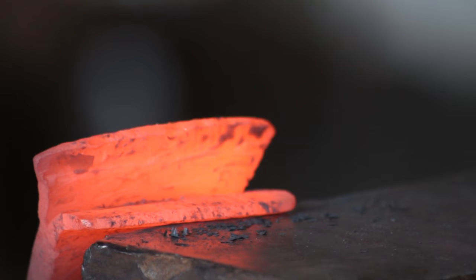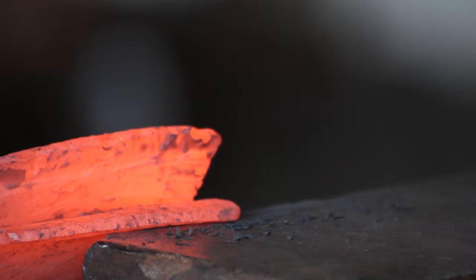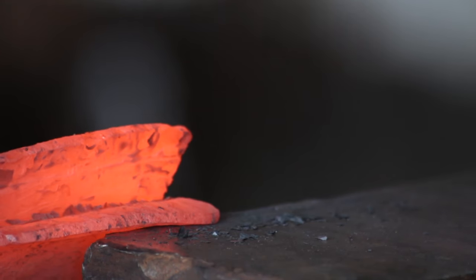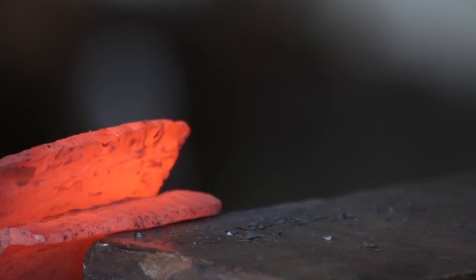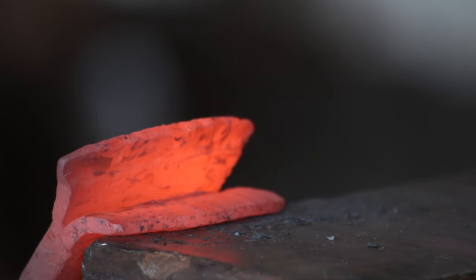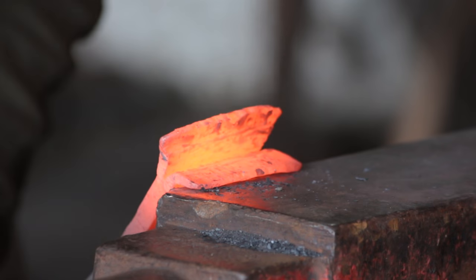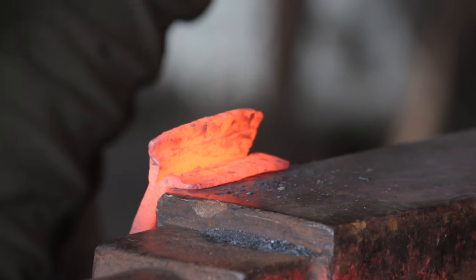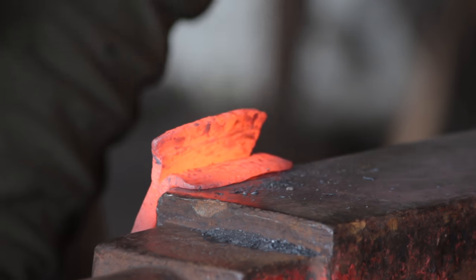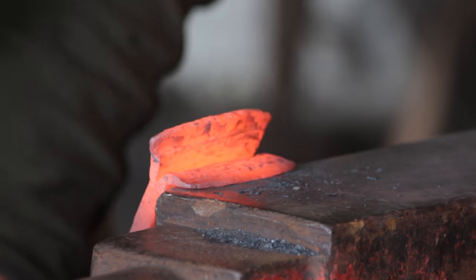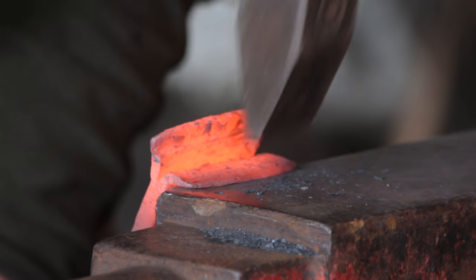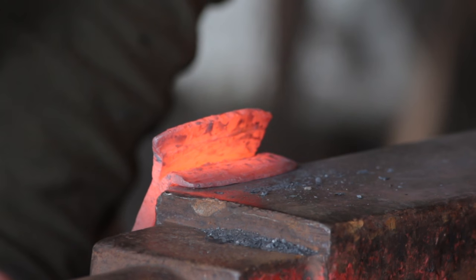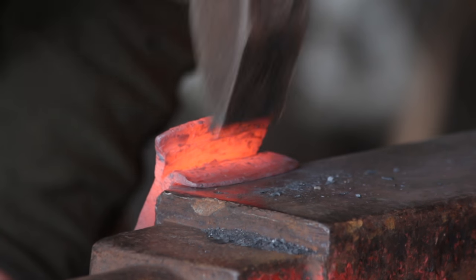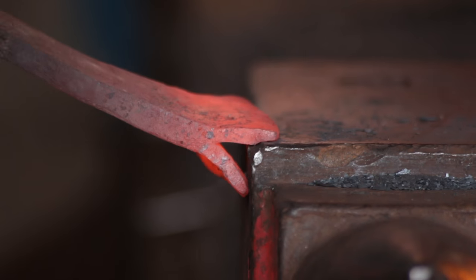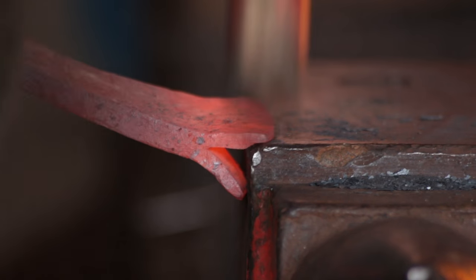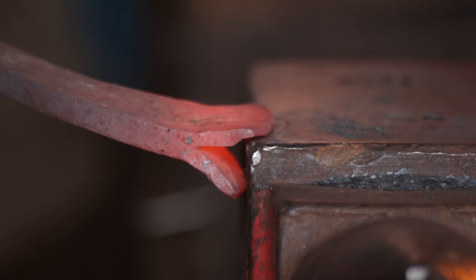So I'm bringing them to a taper, I'm going in with a cross pein to spread them out a little bit as well, to start off with, and then I will come in lengthways with a cross pein just to get that pointed taper on the end. And I'm doing it from the inside to demonstrate. If I do it from the outside, you tend to end up with a step like that, which is quite difficult to get out.